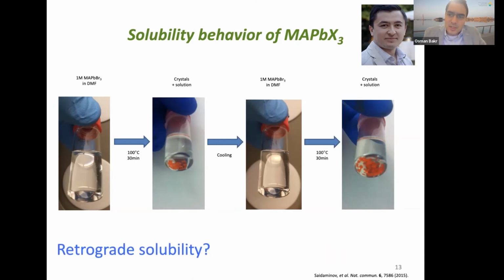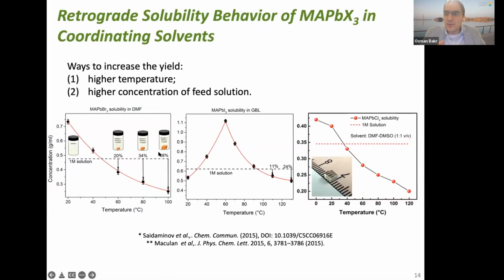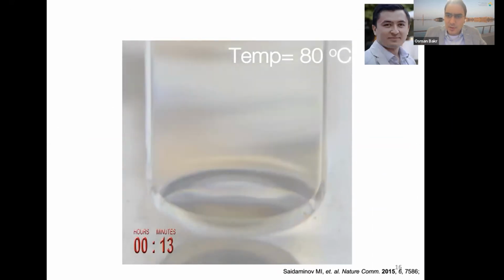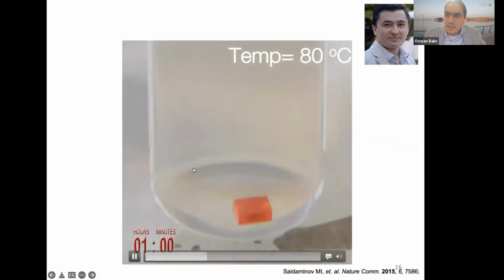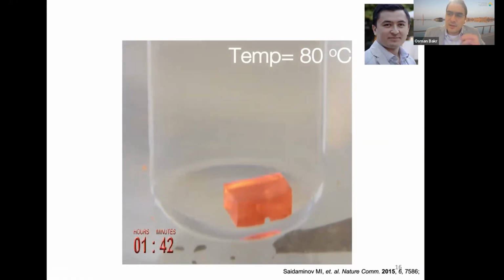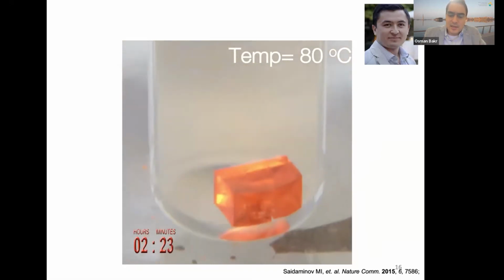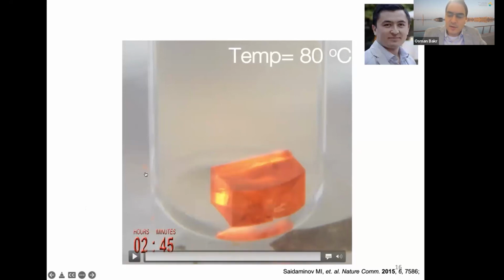This phenomenon is called retrograde solubility, and we noticed that it actually occurs for a wide variety of metal halide perovskites in coordinating solvents. The solubility drops when you raise the temperature, because in a coordinating solvent you form complexes with the metal halide, and when you raise the temperature, you start breaking up these complexes and create conditions for supersaturation. So here's an example of a crystal that normally would take a week to grow, and with this method, if you do it very carefully, you can grow your crystals with supersaturation at a very high rate, in a matter of minutes to hours.